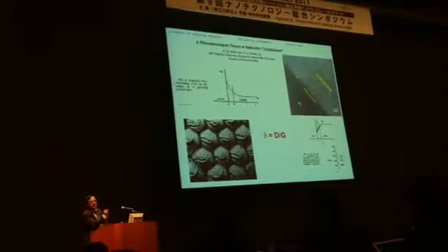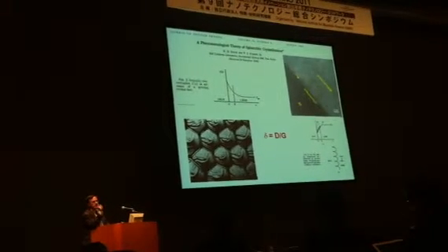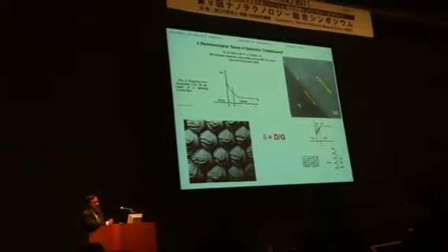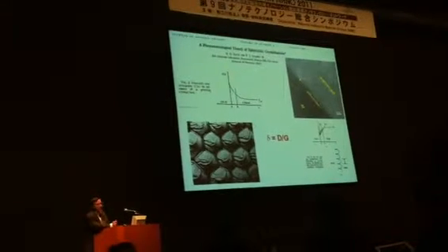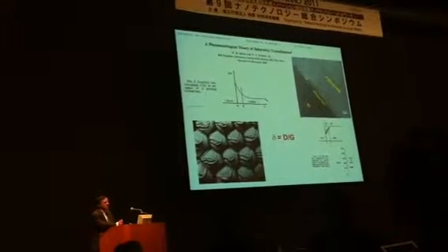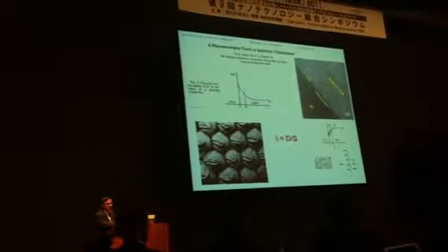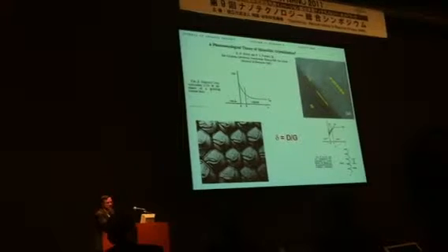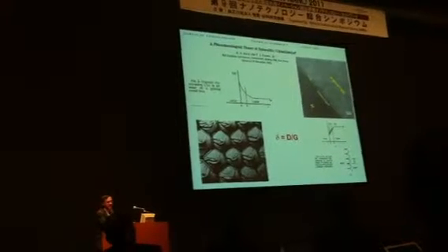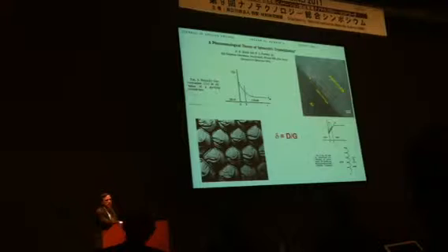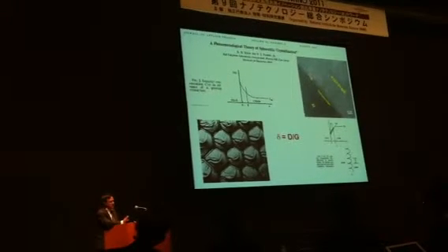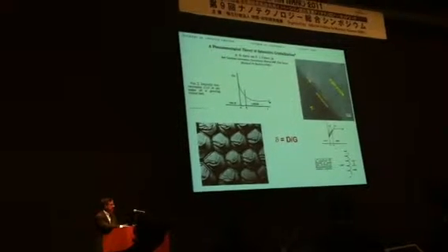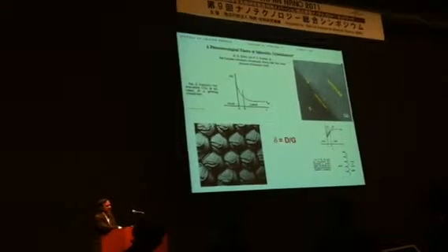What I wanted to do is just show you a very simple example of a classic system that people didn't understand at all. But by taking the techniques that we now have available, you can start to draw a very quantitative picture about what is going on. The folklore of a phase separation of these systems is nonsense. It's really a situation where you have ordering that's driving a sequestration of the PCBM into intercrystalline regions, which gives rise to structures on the order of tens of nanometers in size, which are exactly where you want to be for these systems.